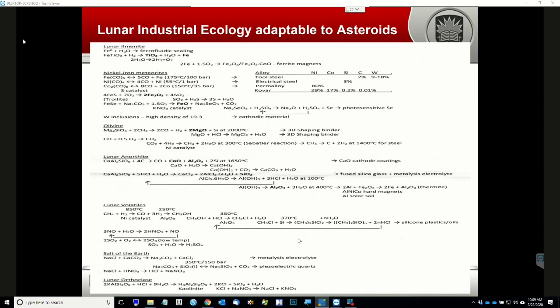I'll skip down through olivine to look at anorthite. Anorthite is a very common mineral on the moon, and this can be processed quite readily through two different processes to extract essentially alumina. Now, on this slide, I've emboldened several materials. These basically are mineral oxides. The importance of that is these can be input into the FFC, the Metalysis FFC process a little bit later, which will be the next slide. So here, looking at anorthite, we can extract calcium oxide and alumina.